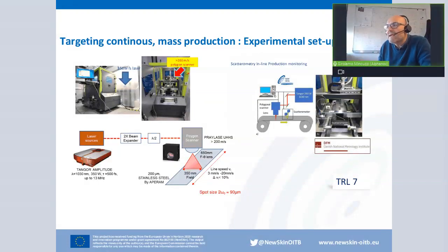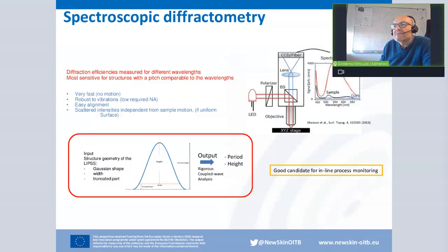The machine includes a system for inline monitoring, based on diffractometry. Basically, we measure the light diffracted by the regular structures that are generated by the laser on the surface, and we compare the spectrum we obtained with the theoretical spectrum that has been calculated, making a hypothesis on the structures we are generating. We choose the one that best fits the experimental results, and this way we can calculate, for instance, the period and the depth of the structure that we have generated on the surface.